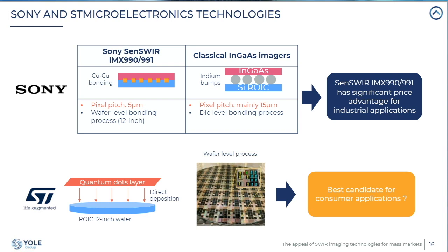STMicroelectronics takes a different direction, focusing directly on consumer and automotive applications using quantum dot technology. The advantage of quantum dots is that the material absorbing SWIR wavelengths can be deposited directly on the wafer, leading to a wafer-level process and significantly lower cost than InGaAs. We believe quantum dot technology is currently the best candidate for consumer applications in the short term.